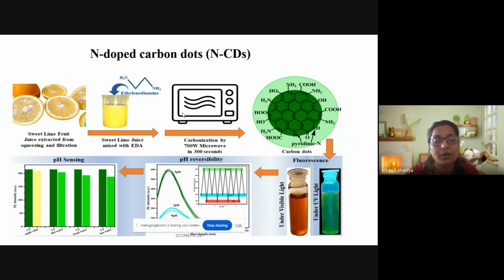So in my research work, I have prepared two types of carbon dots. First is the N-doped carbon dots, and second is the P-doped carbon dots. This is the pictorial representation of the nitrogen-doped carbon dots, in which we have used sweet lime juice extract. This fresh filtered sweet lime juice extract is mixed with EDA, ethylenediamine, which is a rich source of N-dopant ions. Then the mixture solution was irradiated in a microwave for 5 minutes, and then the final solution was filtered, centrifuged, and filtered using a micro syringe filter.